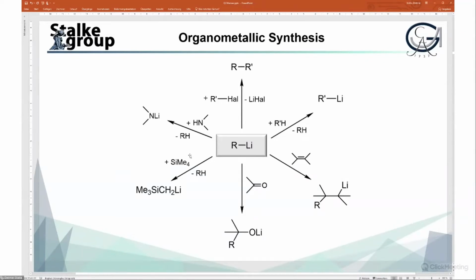Even material which has the reputation of being very inert, like TMS, you can react with lithium organics and then convert that into a starting material. Coming to the lithium amides, which are then deprotonated by the lithium organics and normally form a lithium-nitrogen bond.